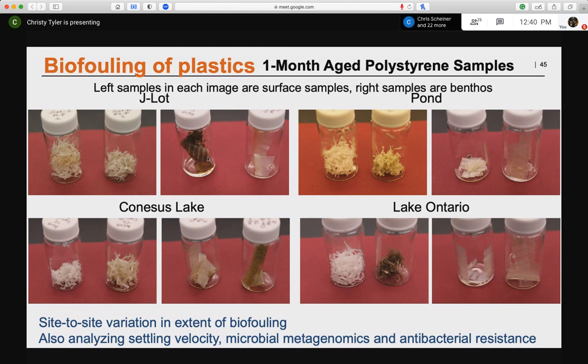If we look at Conesus Lake, we see a difference. You're getting a fair amount of film growth on the surface in the benthos, whereas at the surface, we're getting more of this yellowing. You can see that there's site-to-site variation in the extent of biofouling.